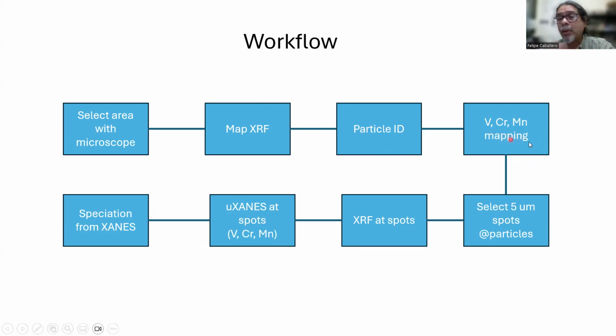We do the mapping of vanadium, chromium, and manganese. And when we identify the particles we want to study, we select 5-micron spots at each particle. We select at least 3 spots where we will perform X-ray fluorescence to confirm that this spot contains chromium and manganese, or chromium or manganese, and then do micro X-ray absorption near-edge spectroscopy in these very spots at the vanadium, chromium, or manganese K edges. And then with these spectra, we will perform the speciation to see which is the oxidation state, which chemical species are present at each spot, and then compare the different samples, either the rainy season or the dry season.